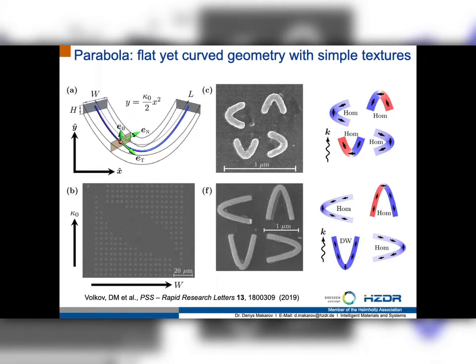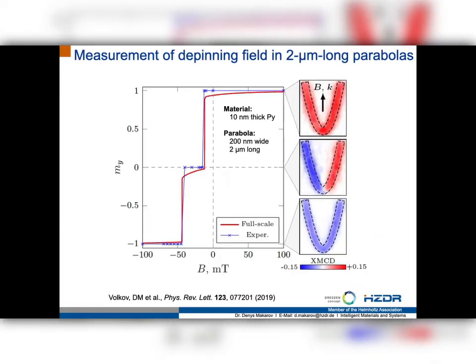In this case, you will have a domain wall at the apex of this parabola, right? Now, if you monitor the switching of this parabola in a magnetic field which is applied along the symmetry axis of the parabola, you will be able to observe two switching fields. The second switching field, at about minus 50 millitesla, is due to the magnetostatic shape anisotropy, expelling the domain wall from the system and reversing the system. And the first step is actually something which is very interesting. The first step does not exist in a stripe which is not geometrically curved. And this is a parabola out of permalloy.